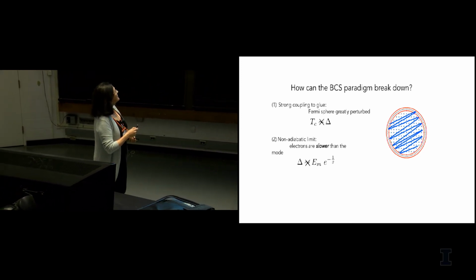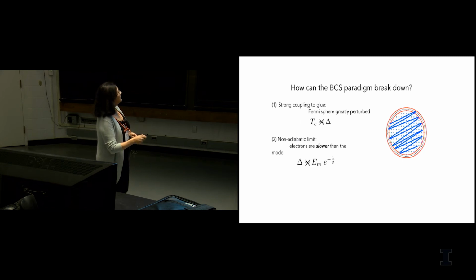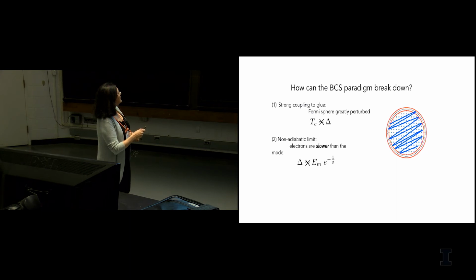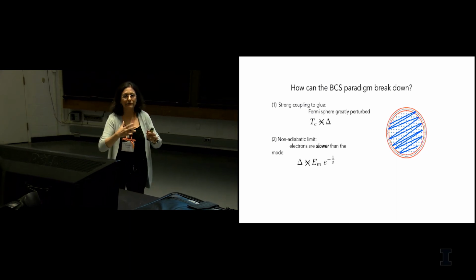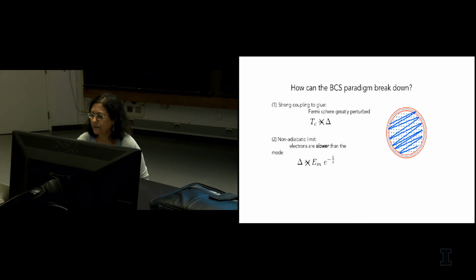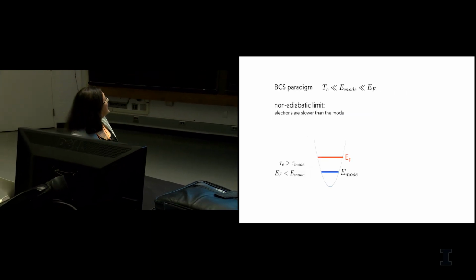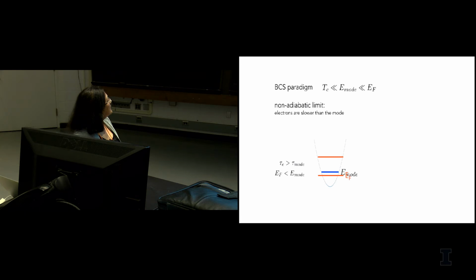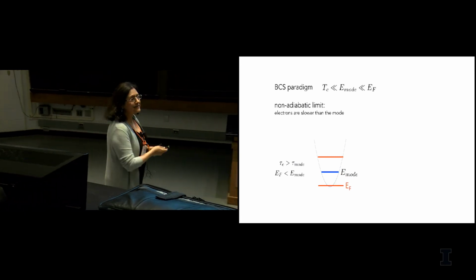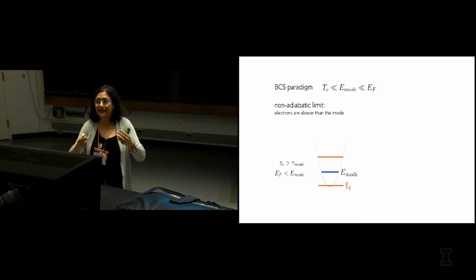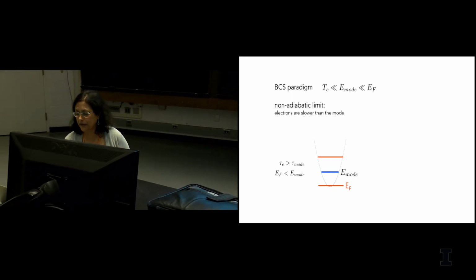One is the coupling to the glue, whatever that might be, greatly perturbs the Fermi surface, in which case Tc is not given by delta anymore. Or you might have a situation where the electrons become slower than whatever mode is trying to couple them. And so that takes you into a non-adiabatic limit. You can see that can happen in very low density systems, of which several are now becoming possible.